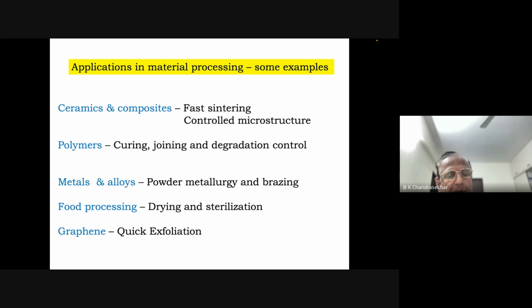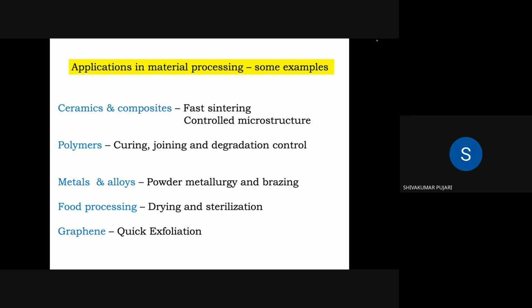This process is quite time consuming, because you need to heat the material to 1000 degrees centigrade, and you cannot heat it very fast by conventional methods. And we in Enerzi microwave system are able to do this task within less than 5 minutes. We take the treated graphite material, expose it to microwave, and within 5 minutes or even less, the temperature goes up to 1000 degrees centigrade and exfoliation takes place. Any questions on this? No, sir. Okay.